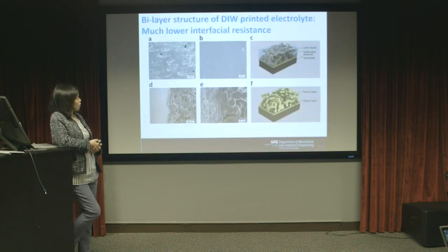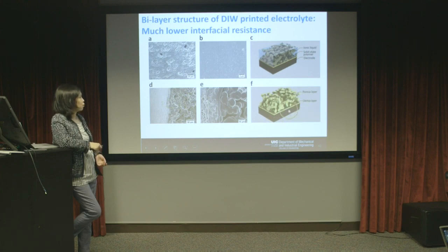And if you observe the printed material more closely, you will see that between the electrode and the printed electrolyte, we can have two different layers. One layer is a dense layer, which is adhering to the electrode surface. And then in the center is a porous layer. So this is because of the formation of the two layers of electrolyte.